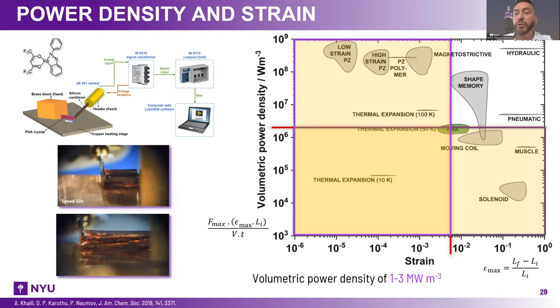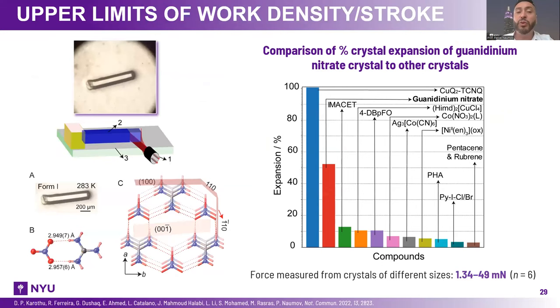So this is the beauty of this work, that basically we work with very, very simple systems. This is another example which has been discovered a long time ago, but we had the chance now to correlate it or to compare it with other systems. And we found that it expands about 50% of its original size. And as you can see here from this plot, it's actually number two in the expansion percent of all the crystals reported out there. It is second only to one of the materials, but I have to mention that this material here disintegrates upon expansion. Our material does not, at least for 10 cycles of expansion and contraction.